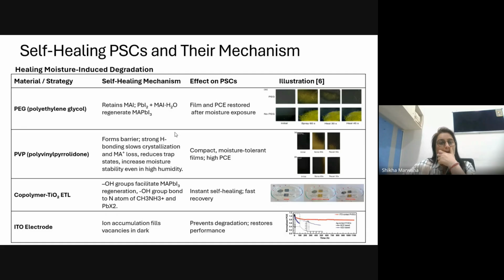As I have said, the impact of the environment is always there. If the external trigger is only moisture, then when we are making the precursor of the perovskite, for example methyl ammonium lead iodide, I can make use of a polymer inside it, let's say PEG, polyethylene glycol. If I use those polymers while making the precursors, I can increase the lifetime of my material, increase its efficiency, or prevent this degradation.